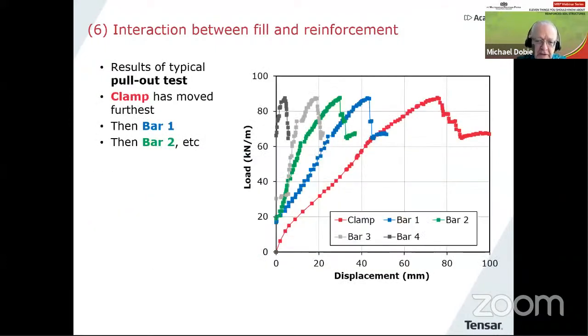Now, this graph shows the load being measured at the clamp versus the displacement. And then the different colored lines represent different points along the geogrid. So the red line would be the clamp itself. And then we get bars 1, 2, 3, and 4 going all the way back to the buried end of the geogrid. And clearly at the far end of the geogrid, the displacement is much smaller because as you load the geogrid, it by itself becomes longer.